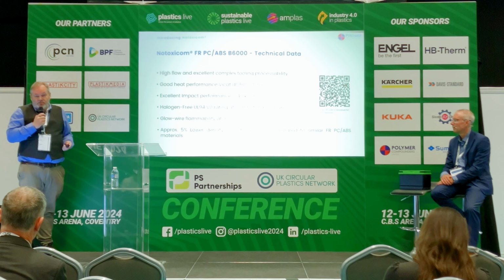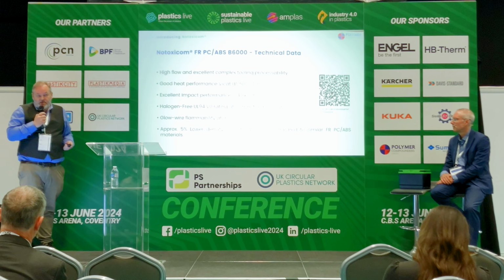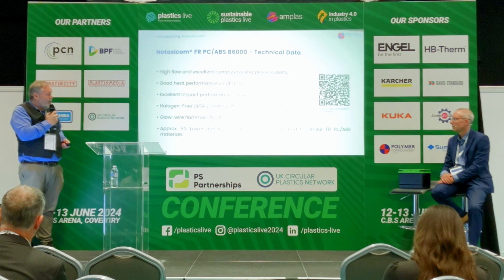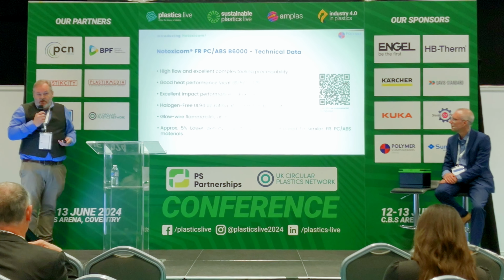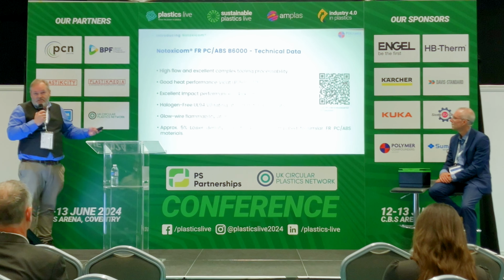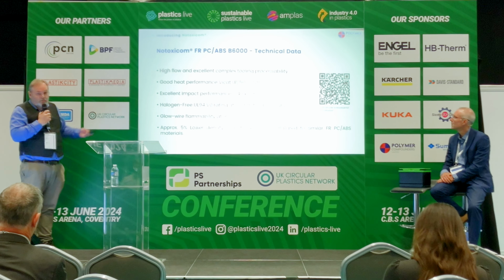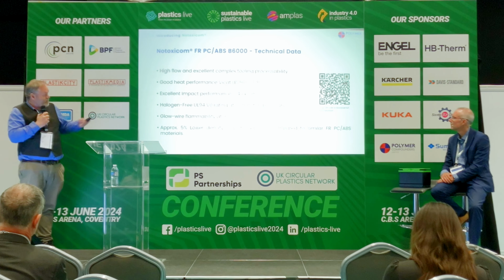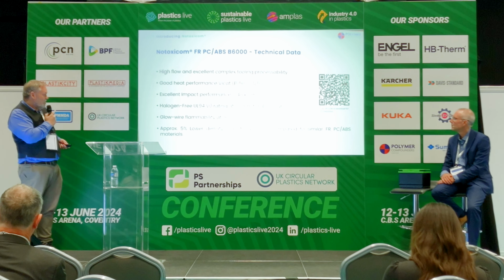Our product, 100% polymeric, keeps that thermal performance. So we have a VICAT that's 10 to 15 degrees higher than most of the FRPC ABSs on the market. Its impact is 46 kilojoules per metre squared, which, as we are a massive automotive supplier, we know is high enough for a vehicle crash tested interior. Their non-FR PC ABSs, which have been crash tested, are at the level of this impact result.